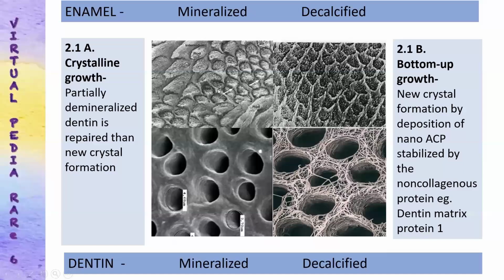In situation like this, where there is some amount of demineralization, it can be cured or treated by the crystalline growth mechanism. Whereas the situation like this, when there is complete loss of minerals and only inorganic portion is sustained, this is repaired by the non-collagen based protein. The non-collagen based protein helps us to form the nucleation of ACP molecules and then formation of hydroxyapatite crystal in bulk to repair this structure.